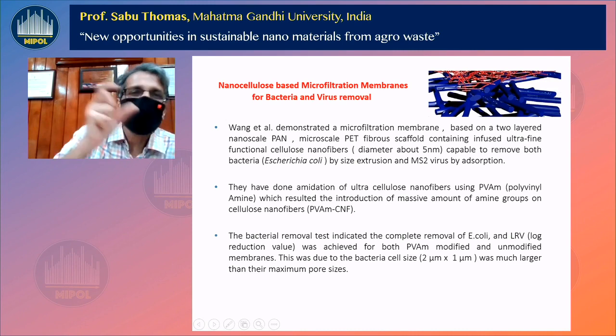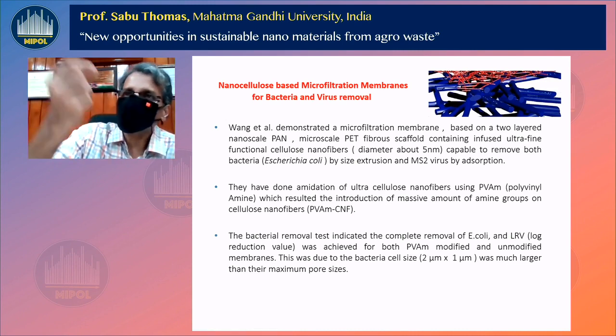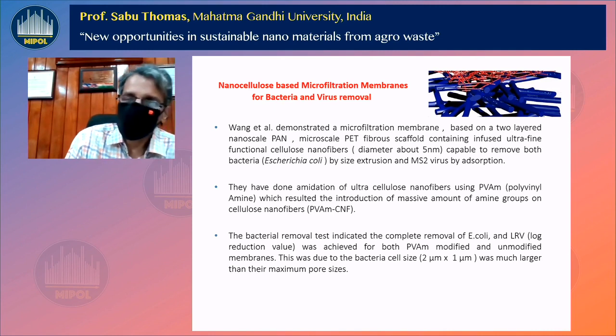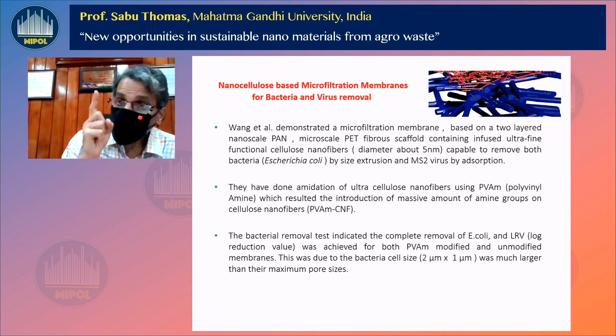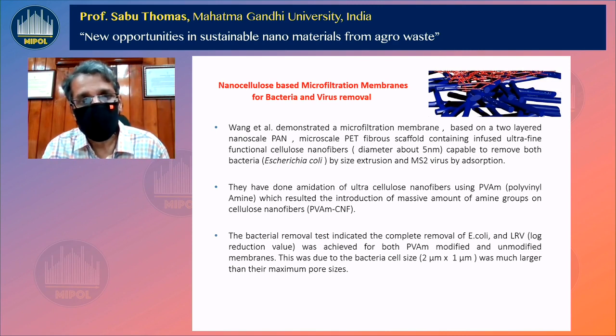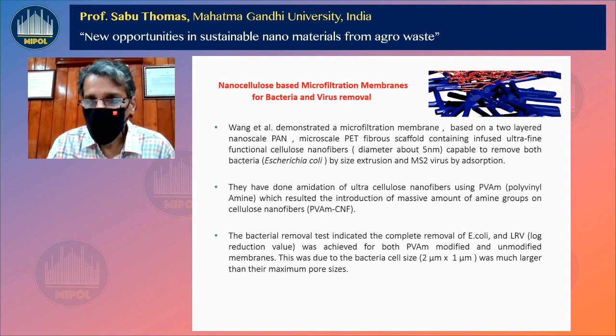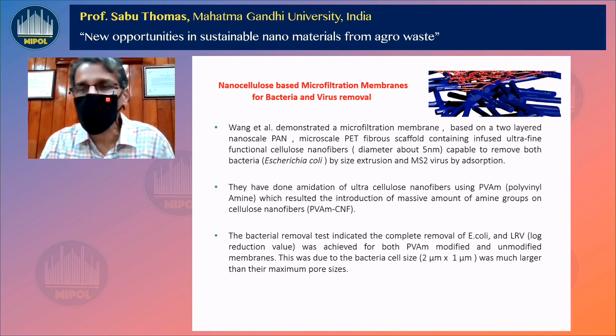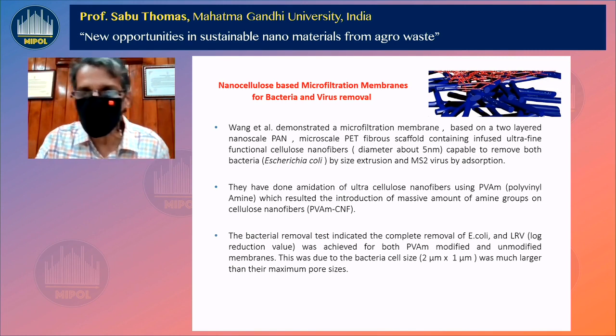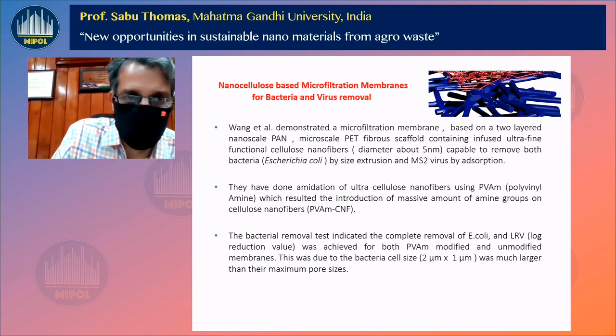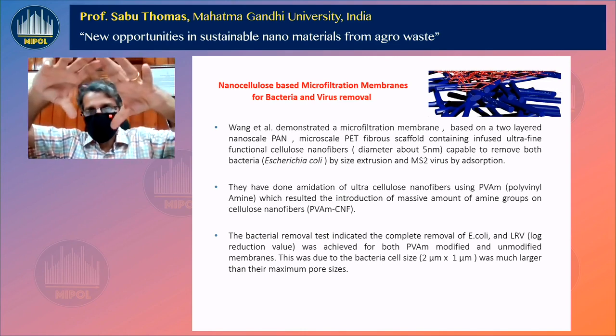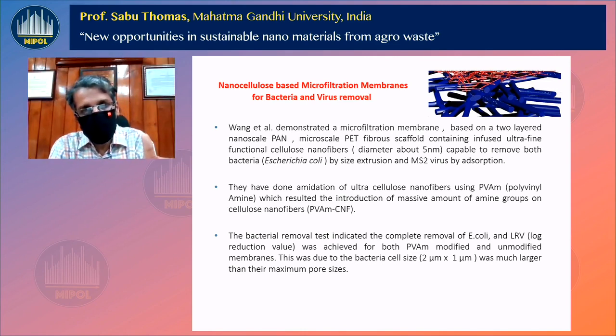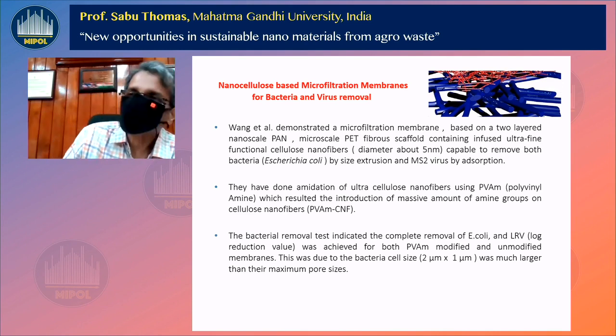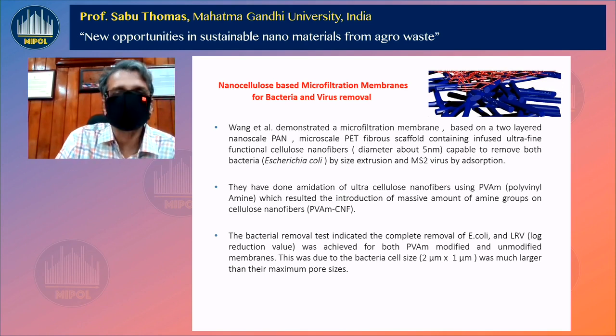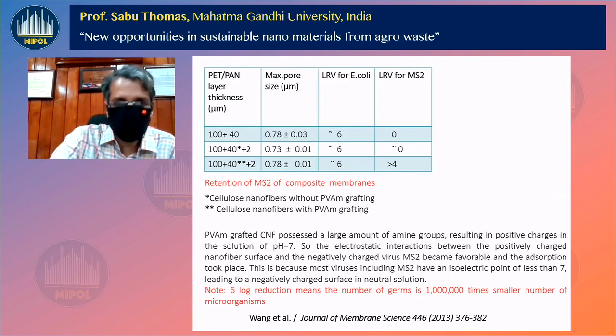You want to remove bacteria and viruses. Bacteria, simple, they're big. By a size exclusion principle, you can remove them because they could be retained by the filter. They're bigger in size. But if you want to remove viruses, they're small. You need to have some chemistry. Simple chemistry, polyvinylamine is the best. You introduce positive charge on the surface of nanocellulose. Put amine functional groups on the surface. Probably you all know that viruses, including coronavirus, have a protein envelope with a negative charge. And you can trap these viruses by electrostatic interaction. So this is again a good way of removing bacteria and viruses.